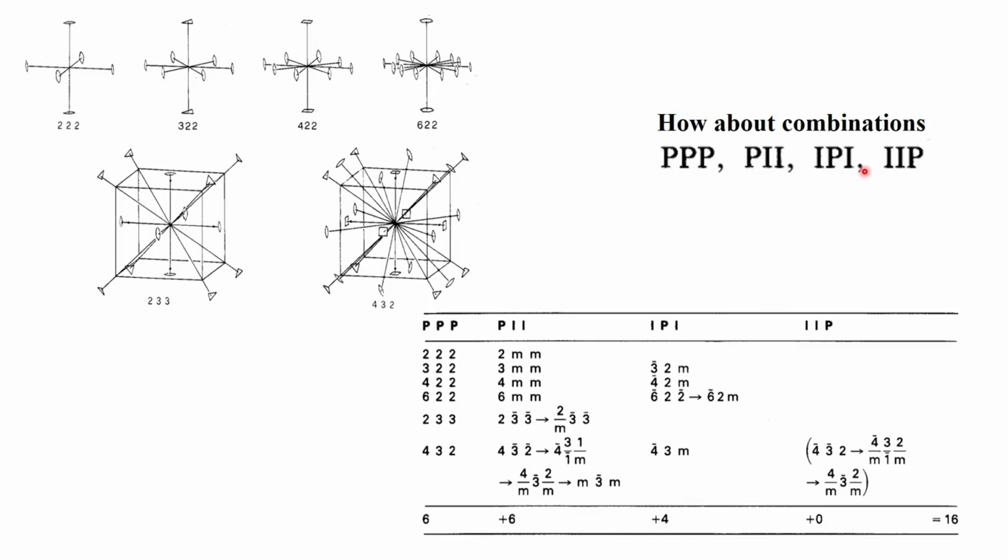So, the direct crystal systems which we can get are the orthorhombic, the trigonal, the tetragonal and the hexagonal systems, and then these two now give rise to the cubic system. If none of these symmetries are there and there is simply a one symmetry or a one bar symmetry, that defines the triclinic system. And in case we have the mirror plane or the two-fold symmetry, it defines the monoclinic system.